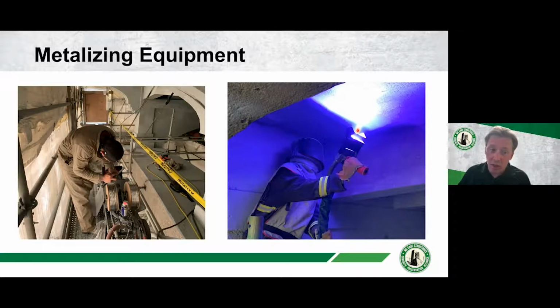They're electrically charged. When those wires touch and they're electrically charged, they short together and start, for lack of a better word, zapping each other. When that occurs, it gets very, very hot, and then that zinc becomes vaporized. We propel that molten zinc that's vaporized, with compressed air onto the surface of the concrete.